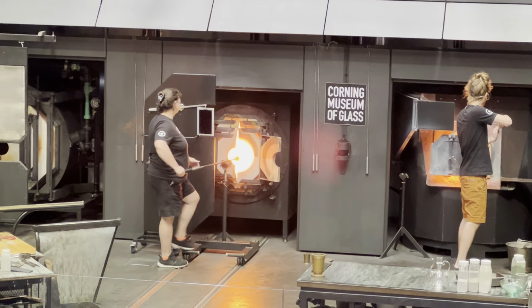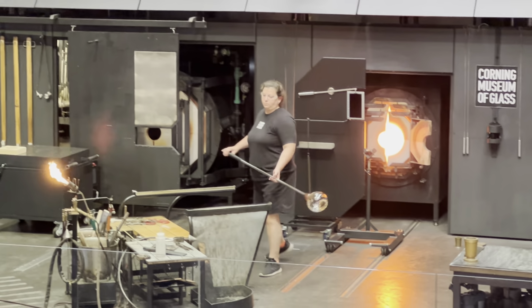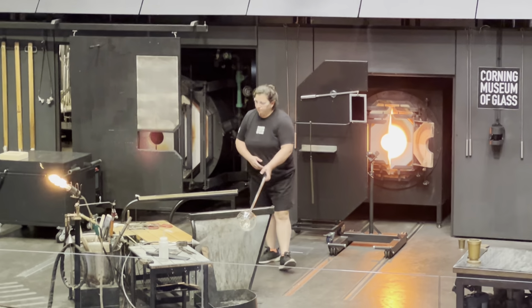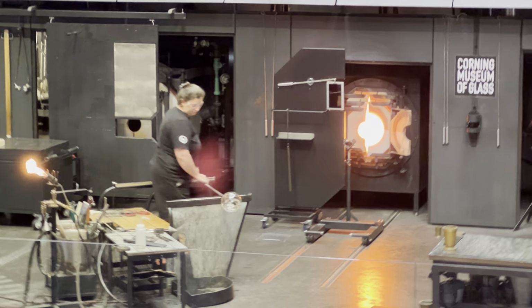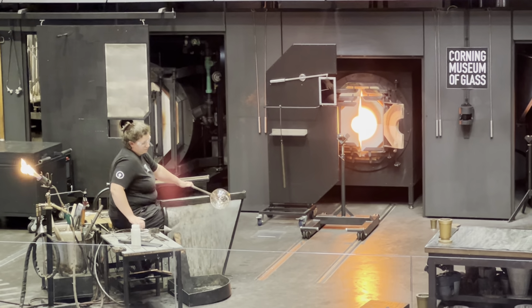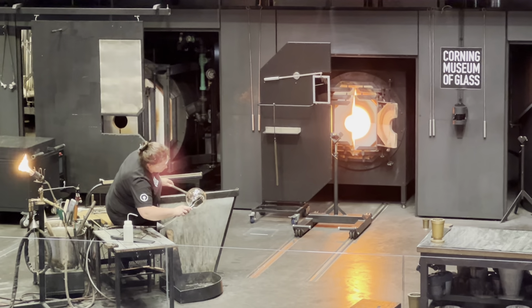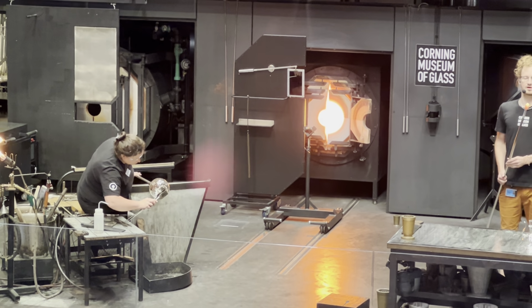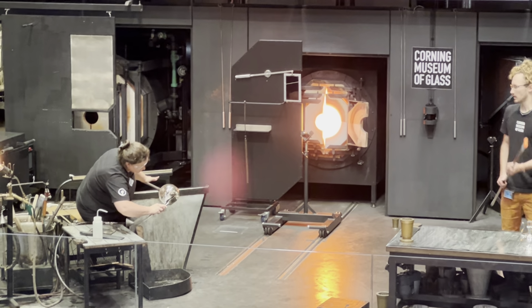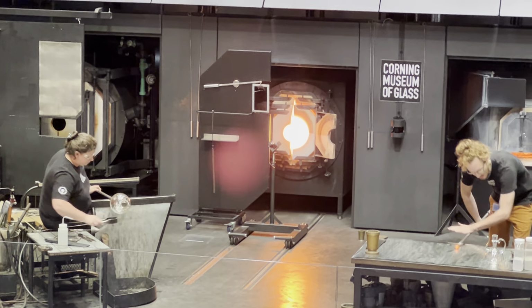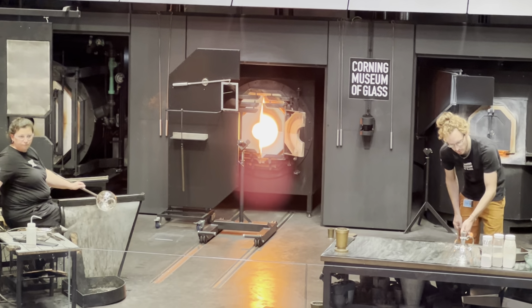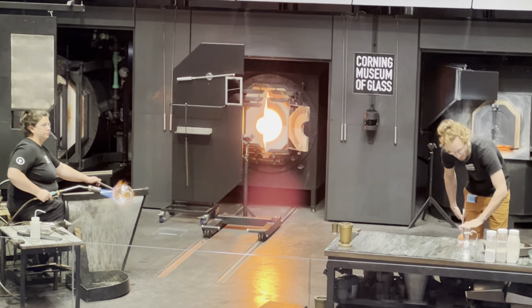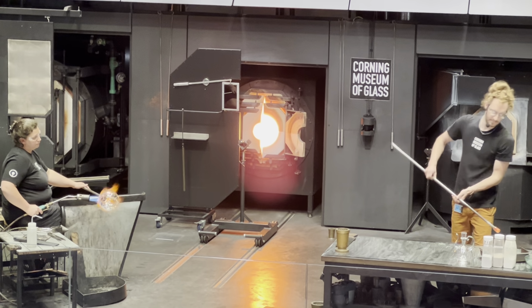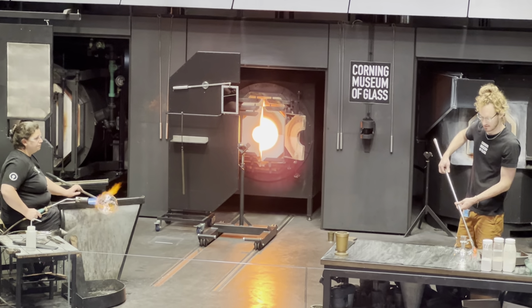We're transferring glass from the blowpipe onto this punty, this temporary handle. And this is really one of the most precarious parts of the process because we do have to break glass. So to be a good glass maker, you have to be a good glass breaker. Catherine created a constriction just off the end of the pipe, and that constriction is how we'll break the glass from the blowpipe. And that will then become the top and the opening of this object.